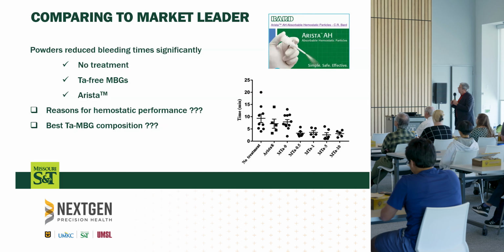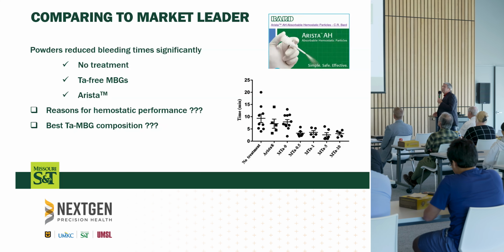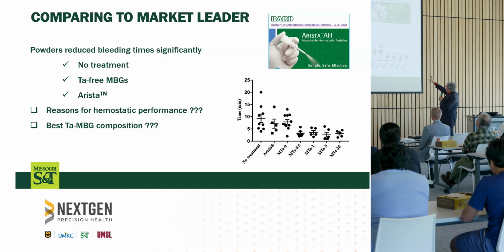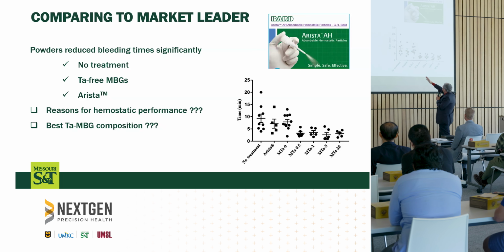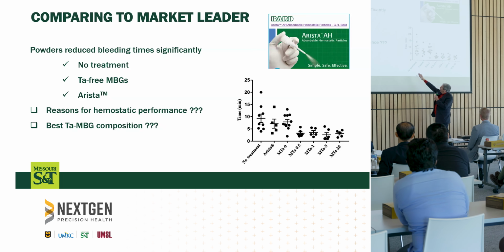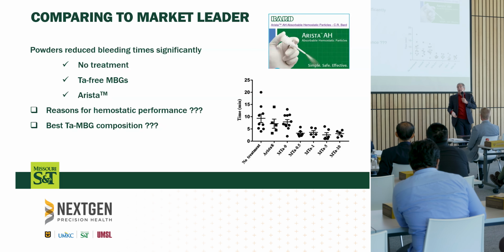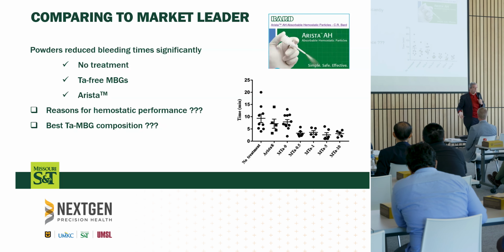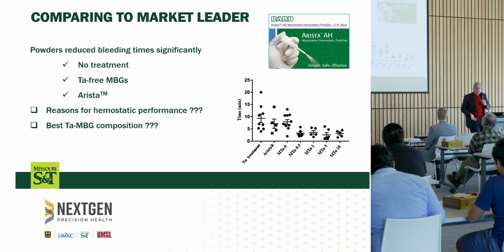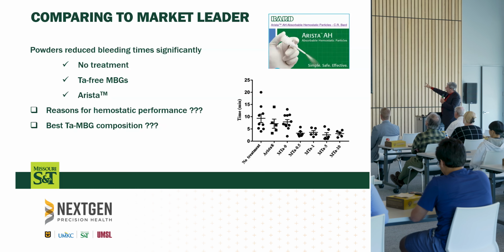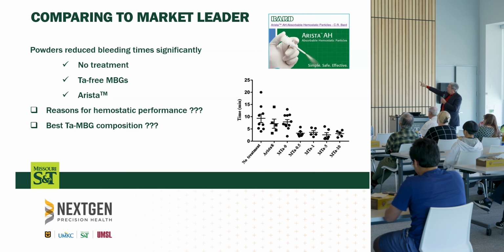So in here, it's a study we published, I think, in about 2019. We took a handful of mice, I think 10 under each condition. We then took some of them and left them to clot naturally. We then applied a small layer of Arista, that's the potatoes, the spuds, on the tail and measured the bleeding time. And then we used our material. And we looked at different increasing iterations of tantalum.